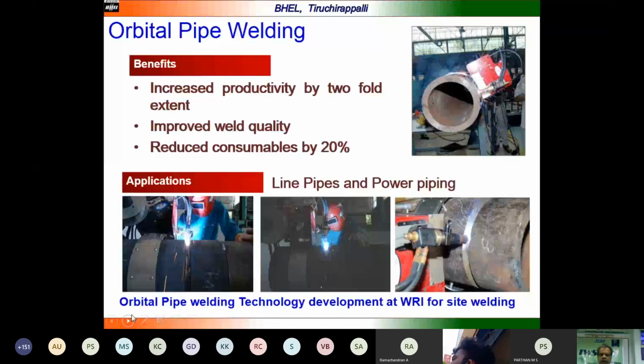One thing here, the orbital welding head cannot rotate fully because of the wire and other things. It can weld from 12 o'clock to 6 o'clock, and again from 6 o'clock to 12 o'clock. Either 6 to 12 or 12 to 6 you can go, but then you have to change the direction. Because of the wire, the gas line and everything, there will be problems if you rotate 360 degrees. So we rotate 180 degrees, and then we can do the welding by orbital pipe welding.